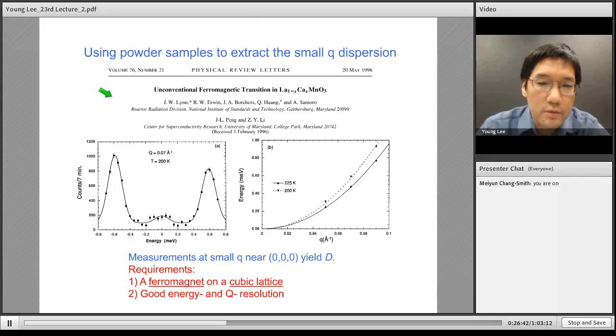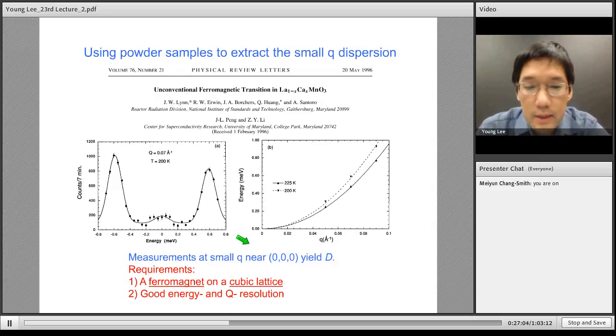And so here's some work done by the NIST group on the ferromagnetic state of manganite. And the idea is to actually measure near the 0, 0, 0 Brillouin zone. So you're near the main beam direction. You need to have good energy and Q resolution just to reduce your backgrounds.